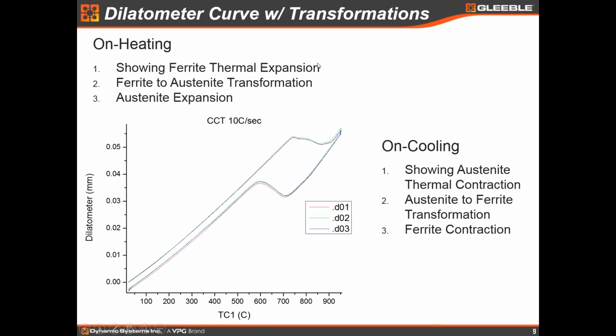But here we see several different phases. So as we initially heat, the on-heating curve, this is simply the expansion of the ferrite. Then we hit a temperature where the ferrite starts to transform to austenite. We get the transformation, and then once we've 100% transformed into austenite, we start again on a linear expansion of the austenite. Then at some point we hold for a few seconds before we start to cool, and then we see the thermal contraction of the austenite. Again, we see that phase transformation going back the other way as we cool, austenite to ferrite, and then we see the linear contraction of the ferrite as we continue to cool down.